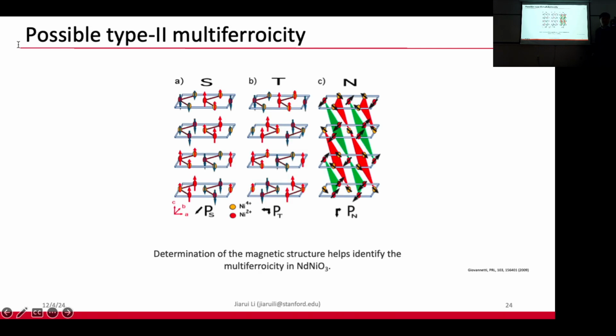So why are people so interested in this magnetic structure? Because there are theories that predict that this material can be a possible type 2 multiferroic material that couples with the magnetic phase transition. And this becomes really interesting because in this material there's a metal to insulator phase transition and also a coupled magnetic phase transition. And right now they are trying to put ferroelectricity in these materials as well, which would add some additional functionalities to the material. So the determination of the magnetic structure can tell us what could be this multiferroic coupling between the magnetic structure and the ferroelectric polarizations.